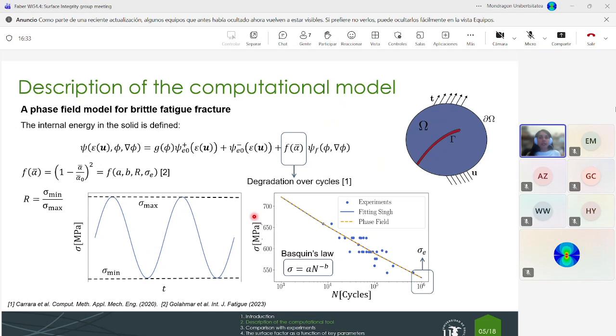When we go to fatigue, we need to include in this elastic energy density, another additional parameter, in the energy of the solid, that is the degradation over cycles. It is a fatigue degradation function that reduces the critical energy release rate over the cycles from one cycle to the other. Again, we have different approaches, and we have used the one proposed by Golahmar et al. in International Journal of Fatigue in 2023.